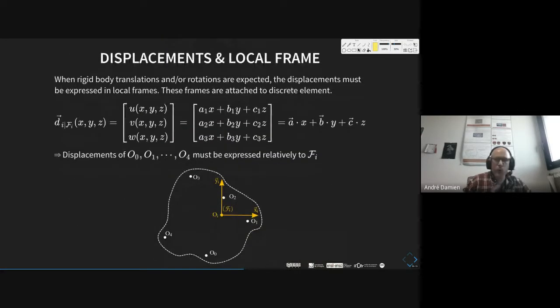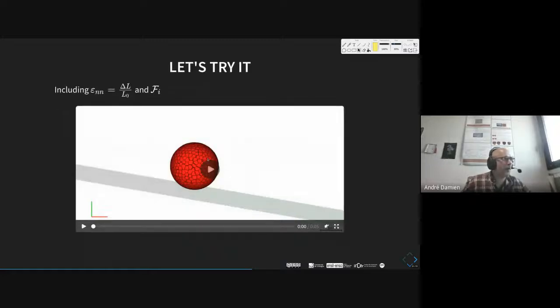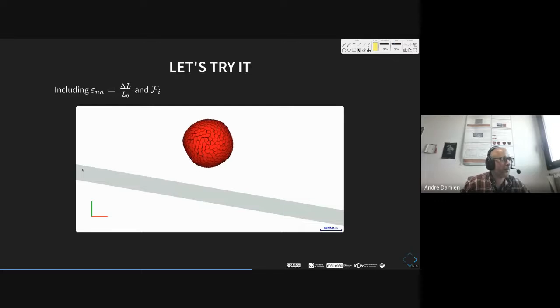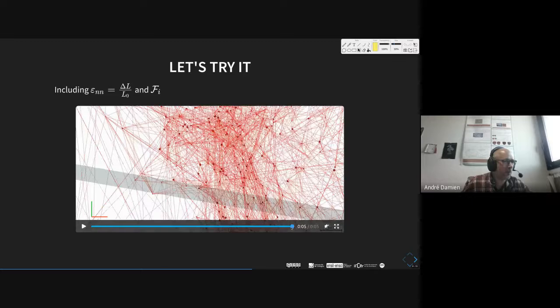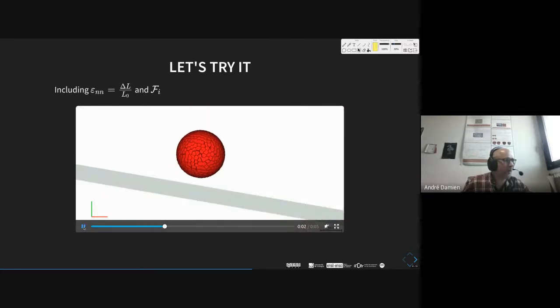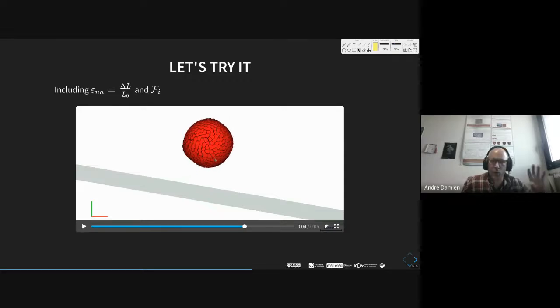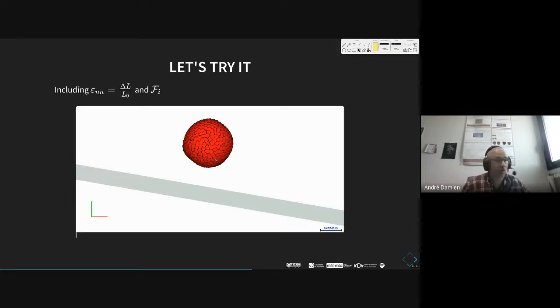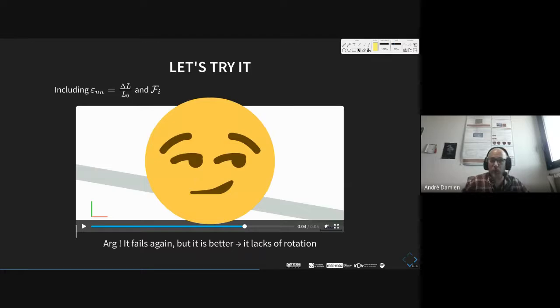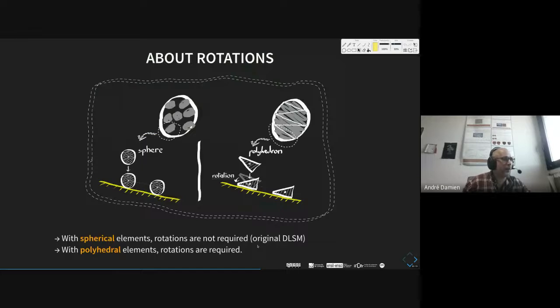Now the second thing is to use a local frame to have a local description of our displacement field. So this is the second trial. So now I move on to another try. So it's quite better, but it doesn't work. So maybe I replay the video just to see. And as you can see, in fact, the Voronoi grains are not rotated. And in fact, this is a problem. So it fails again because it lacks rotation. Here you get the explanation of this problem, because with the original DLSM method, we have spheres. With spheres, there is no problem of rotation. But if we use polyhedra, which are Voronoi cells, it's a problem. We need to take into account this rotation. So now we introduce the rotation capability in this method. So let's try again.